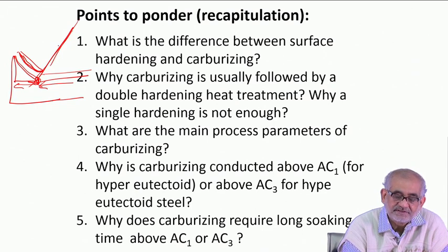That's purely because the temperature here is fairly high, but already if the steel, let's say, is 1.2% carbon or 1.1% carbon, generally these kind of steels are never subjected to carburizing treatment, but for whatever reason, if you are doing anything with hyper-eutectoid, you would rather heat only above the eutectoid and not necessarily go above ACM, because above ACM, you first have to go to very high temperature. There could be subsequent large thermal shock or thermal distortion during quenching. More importantly, because of exposure to much higher temperature, you actually can undergo undesirable amount of oxidation at high temperature.